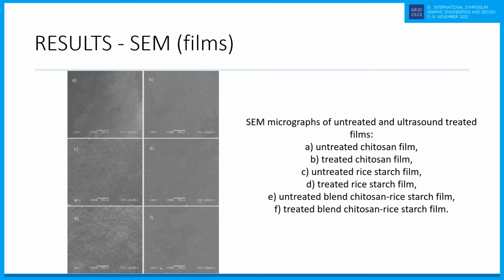In the scanning electron microscope micrographs of the films, you can see that the surface micrographs show a smoother, more even surface on all treated films. It can be seen in figure 3a that the untreated chitosan film is less smooth and not as uniform as the ultrasonically treated film in 3b. The same trend can be seen in figures 3c and 3d, where the micrographs show the rice starch, and figure 3c shows the untreated rice starch, which has a more irregular surface than the chitosan film.